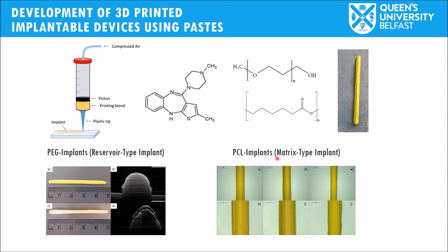Additionally, we used a similar approach, but instead of using an aqueous suspension of the hydrophobic drug and polyethylene glycol, we used an organic solvent, dichloromethane, to dissolve polycaprolactone and the drug, and printed some matrix type implants, as you can see here. These implants are not coated; they are matrix type or monolithic implants. The drug is dispersed within the polymer. Obviously, it's not as environmentally friendly or patient friendly because of the use of solvent, but technically, if we make sure that the solvent is well evaporated, that should not be a problem for the application of this technology, as dichloromethane is used for certain specific pharmaceutical applications.